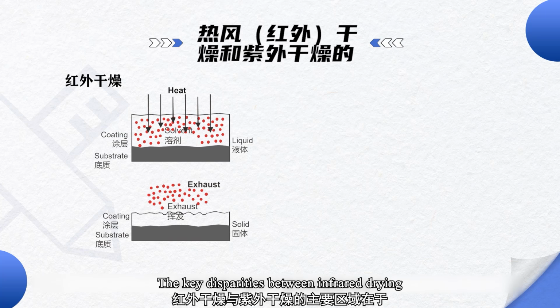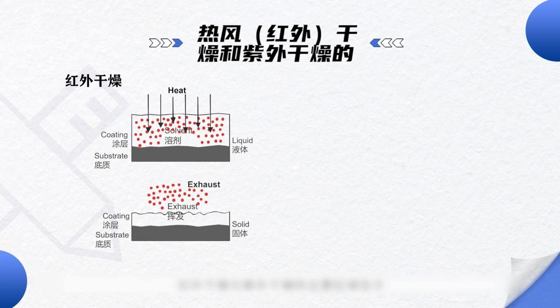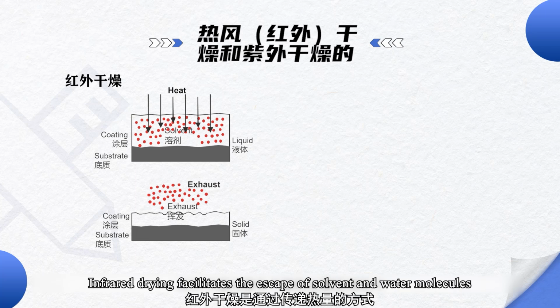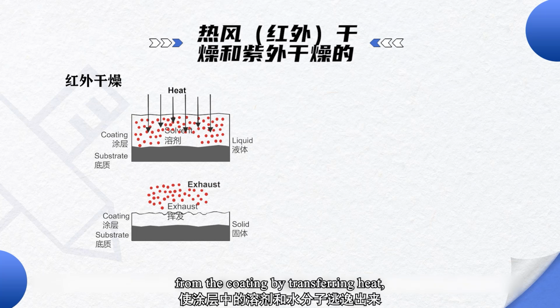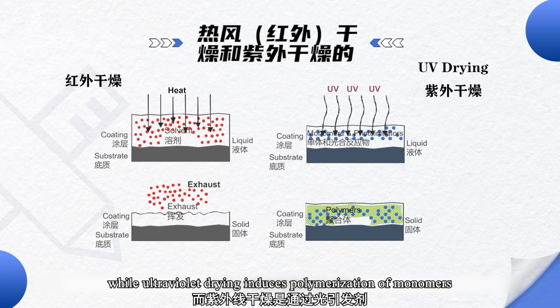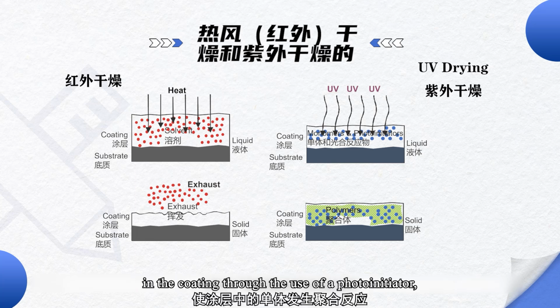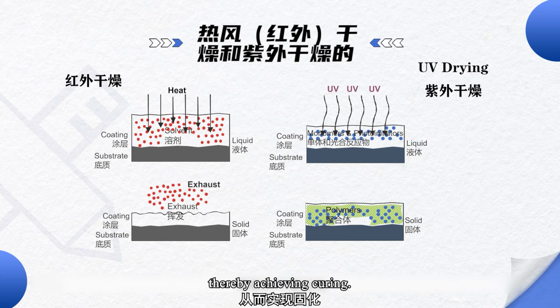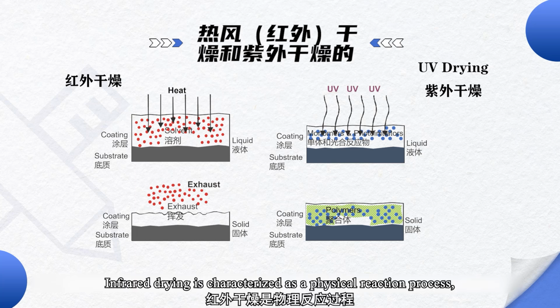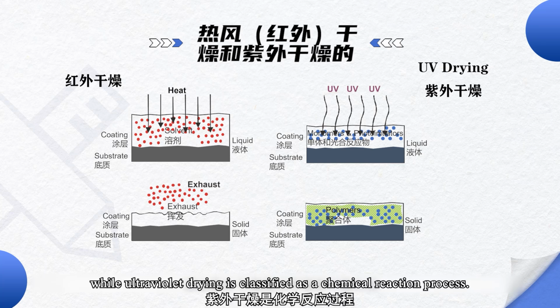The key disparities between infrared drying and ultraviolet drying are as follows. Infrared drying facilitates the escape of solvent and water molecules from the coating by transferring heat, while ultraviolet drying induces polymerization of monomers in the coating through the use of a photoinitiator, thereby achieving curing. Infrared drying is characterized as a physical reaction process, while ultraviolet drying is classified as a chemical reaction process.